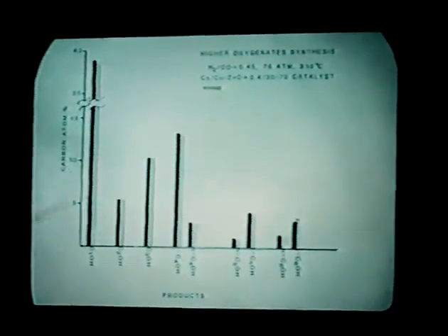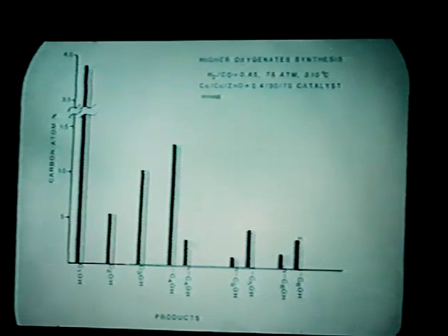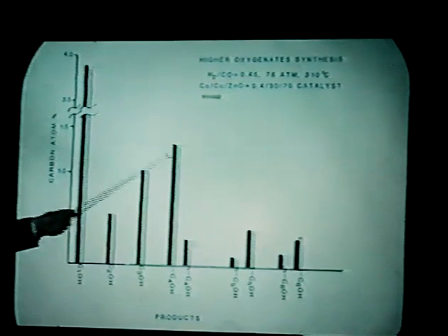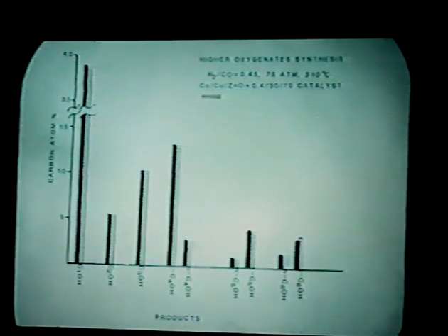And here is how it works. Often we think that our analytical error is actually greater than the error of this model. It's a satisfactory model. In terms of product composition, you can get composition in which the ethanol is at minimum, as I say, because it's rapidly converted to linear propanol, which is rapidly converted to isobutanol. The black bars are experiment, and the red bars are the model. There are some esters in the product and a number of other products. But basically, as people know pretty well, in this system you can make methanol and isobutanol as dominant products. Governed or guided by the model, you can modify the reaction conditions so that you can make these one-to-one. But this will not be necessary in what we want to make next.